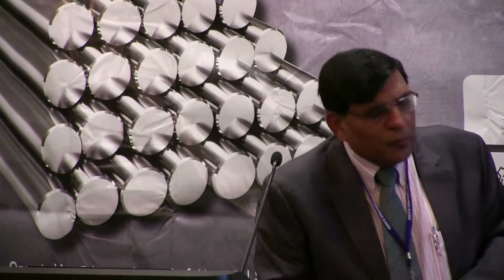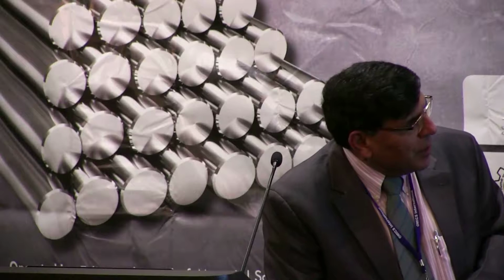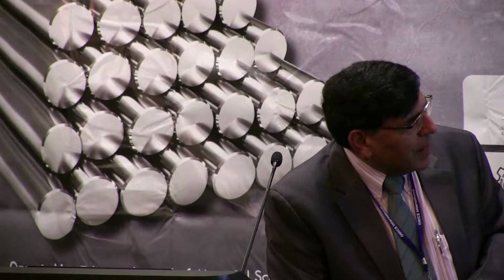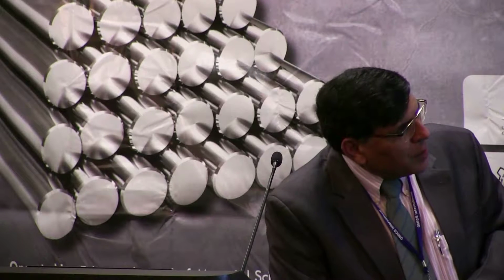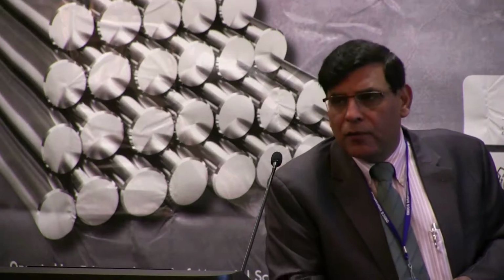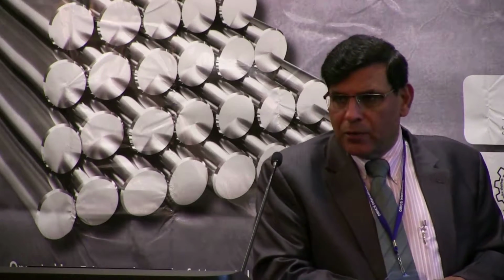The most important part was whether the coating is transparent or not. So this is exactly, you can see, the blue one is the glass, and this is the heat-treated coating, which is showing exactly the same kind of transparency as the original glass. And that is what the most important part was.